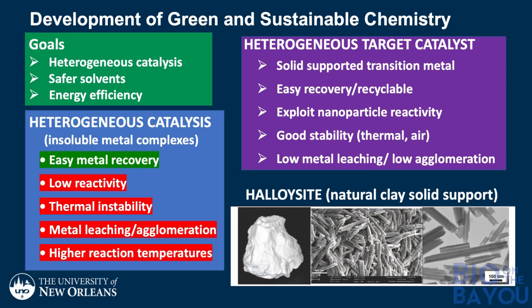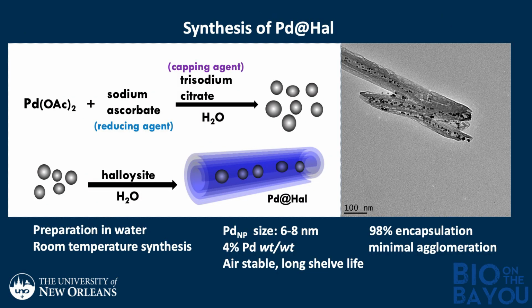And these nanotubes basically are empty inside, maybe with waters of hydration, but basically you can fill these with different types of molecules. And we thought this would be a great place to put metal nanoparticles to stabilize them and essentially provide a reaction surface for them to work at. Now, our intellectual property basically surrounds essentially the preparation of these nanoparticles and encapsulation in the halloysite. We were the first people to put palladium in here, but others had put in gold and silver. But really, our intellectual property focuses on the fact that we do this all in water. Okay, we make these nanoparticles in water.